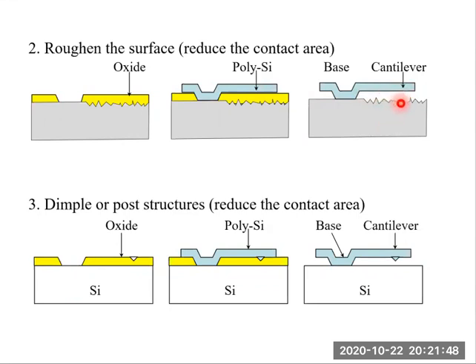Then during the releasing and drying process, a meniscus is formed underneath the cantilever, which will push down this cantilever towards the substrate and cause a contact. However, when it's completely dry, what will happen? When this meniscus disappears, when the water trapped underneath completely evaporates, what will happen? The cantilever will release. Very good. The cantilever will bounce back.